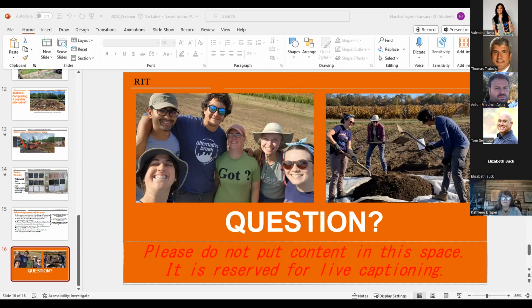Harshal? Yeah, so Elizabeth, what we have done is we are not taking any of the mesh bags and the material out of the bins. So every time we need to move the bins, we are taking the whole set of the bin out, and then moving it into a different pile. So what we are currently after is the temperature more than anything else, and to actually see whether the temperature is physically biodegrading the films or not, because we are seeing extreme fragmentation, which is good, but does it really translate to biodegradation, or does it just mean that the film is becoming smaller, but not really changing in its properties? It's still that polymer, and that's what we are after currently. Does initial composting really work with these kinds of PBAT based films? Because a lot of the bioplastics which are accepted are starch based, which we know will degrade very quickly in the compost, but these PBAT based films are the real question.